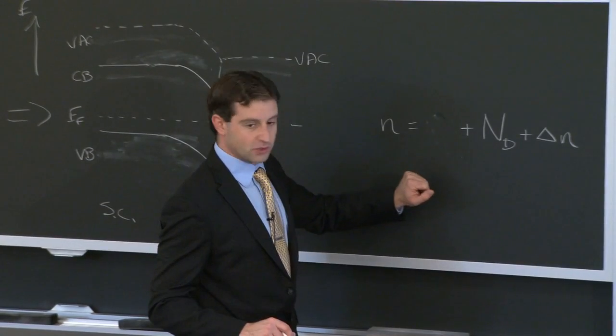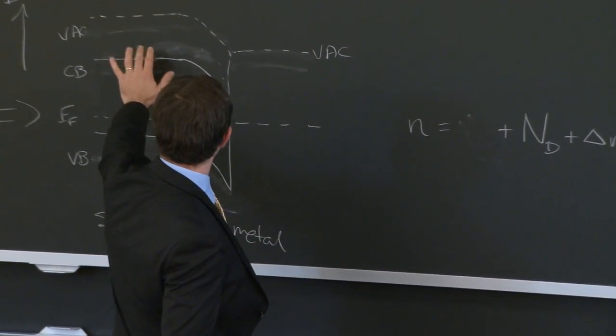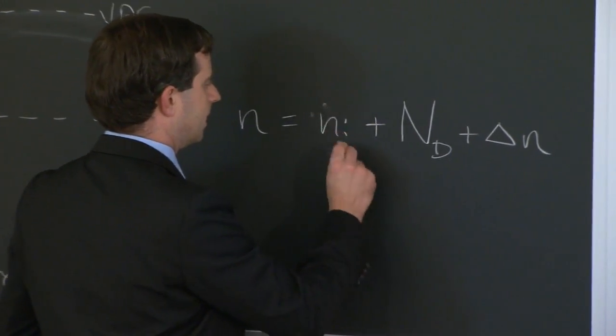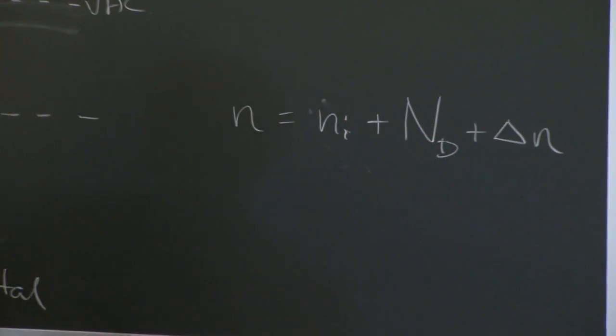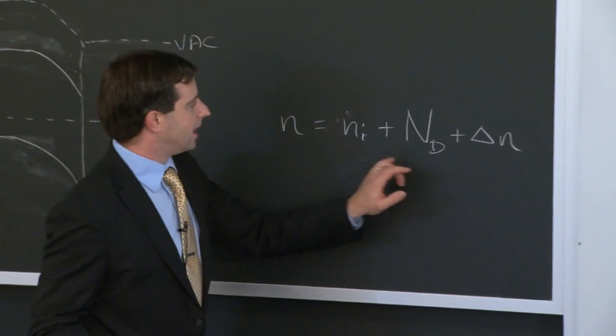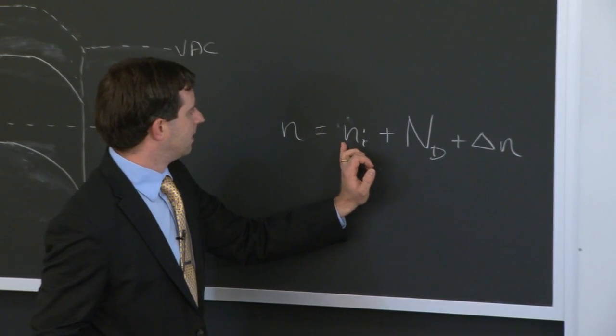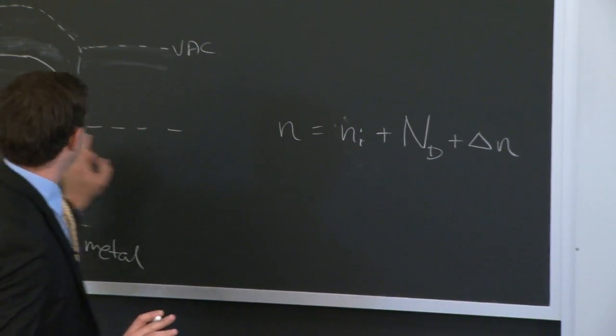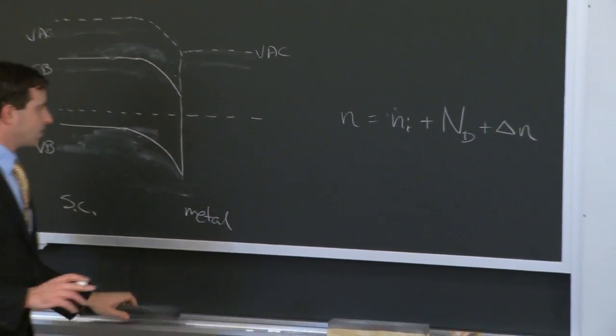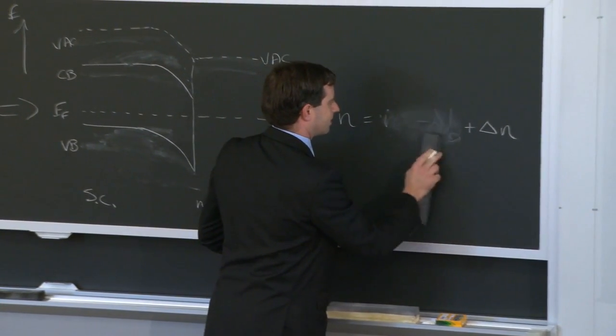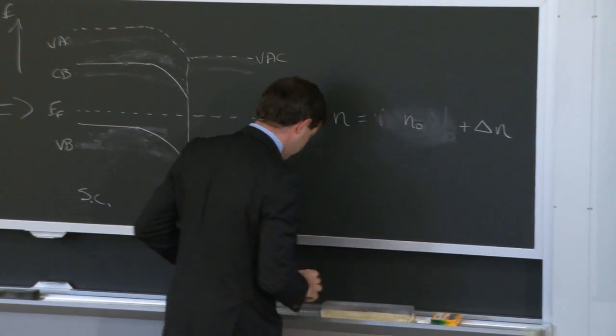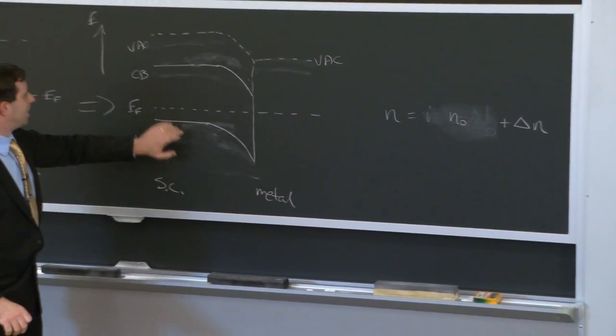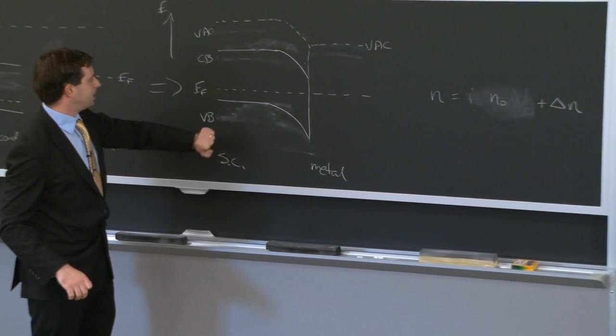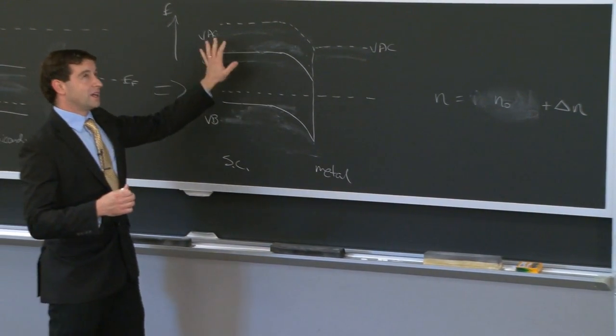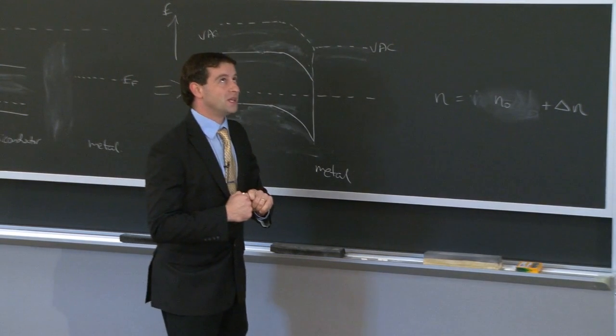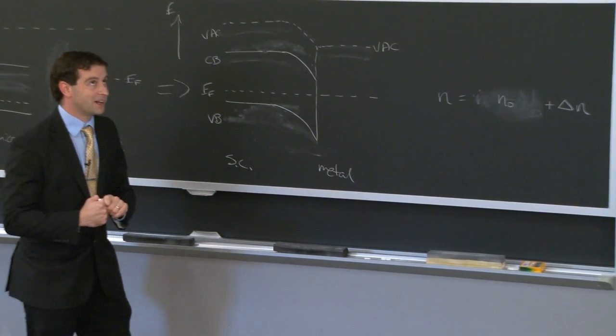This is going to be small, so we can ignore that. Well, actually, no. For the electrons in this case, this will actually be quite big. This is going to be smaller, rather negligible. Let's think this through carefully here. Under equilibrium conditions, let's describe this as N naught briefly. My N naught is going to be rather small because if I have a high dopant density of p-type material, my N naught is going to be equal to Ni squared divided by P naught.